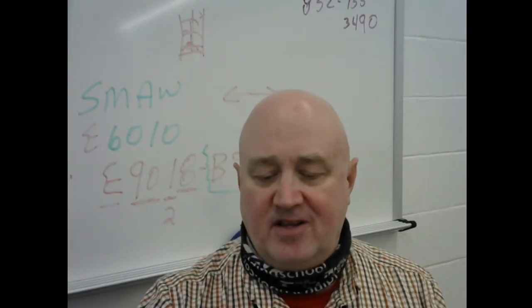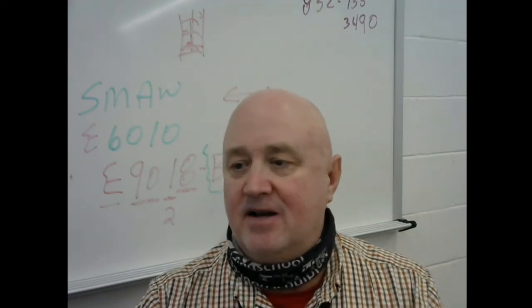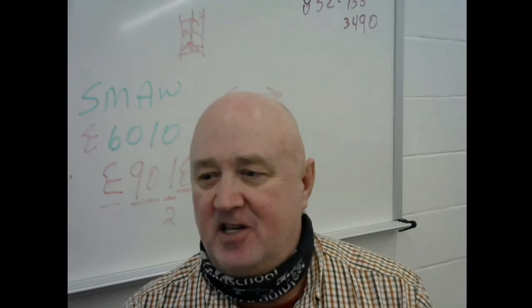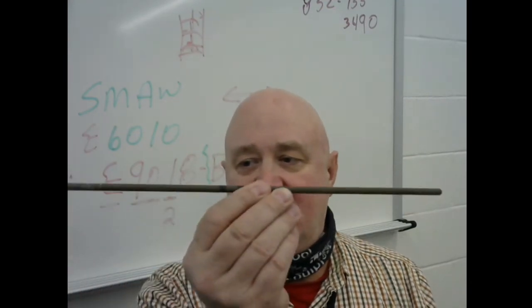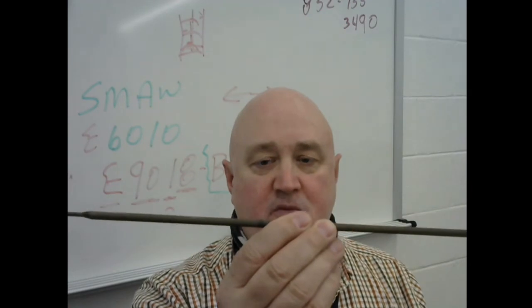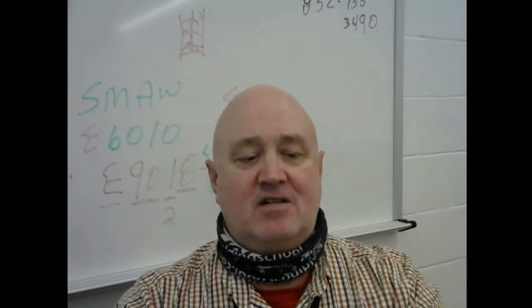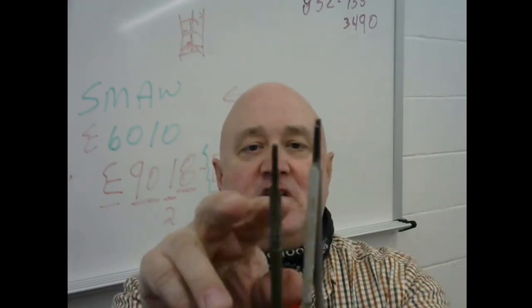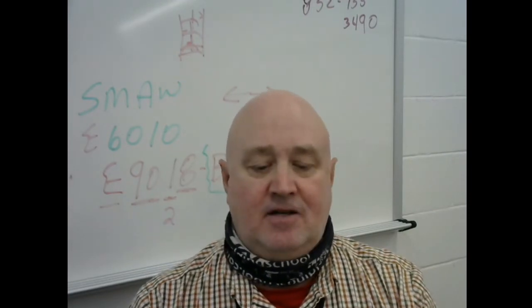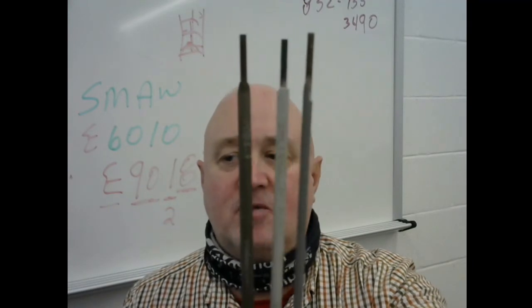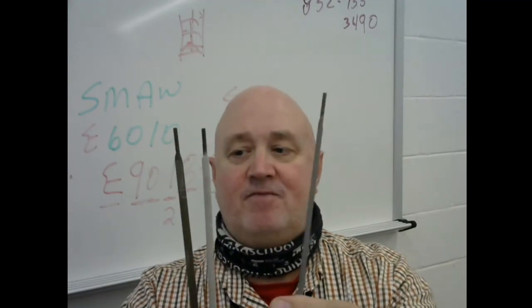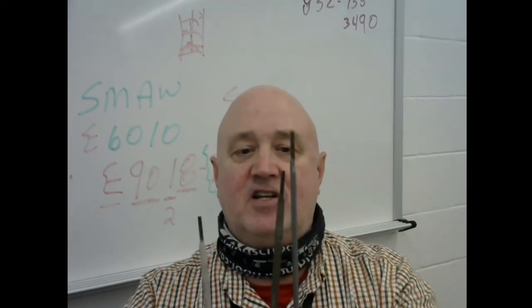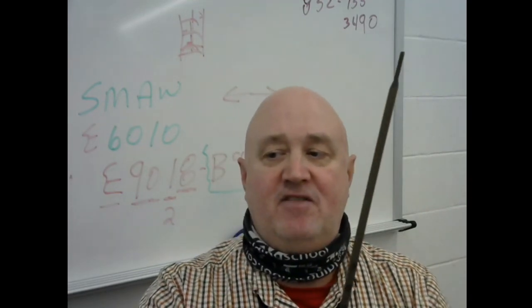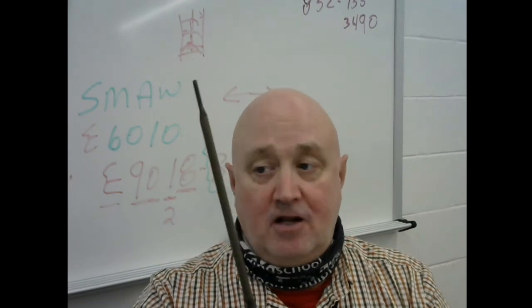When we're talking about the groupings of electrodes, we're talking about what general categories they fall into. So this would be like E7024, which would be a fast fill. All three of these electrodes have the same diameter. Our coat hanger, our electrode, our steel core is all the same diameter. But the difference is the flux. You can see that the flux coating on these three is completely different: my 6010, my 7018, and my 7024. 7024 is going to be the beefiest. It is a fast fill electrode.